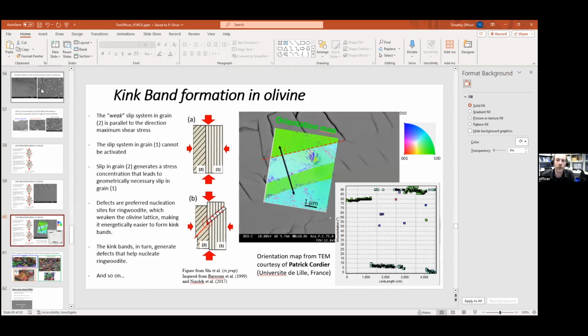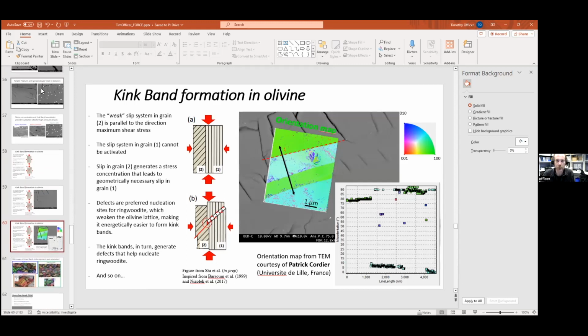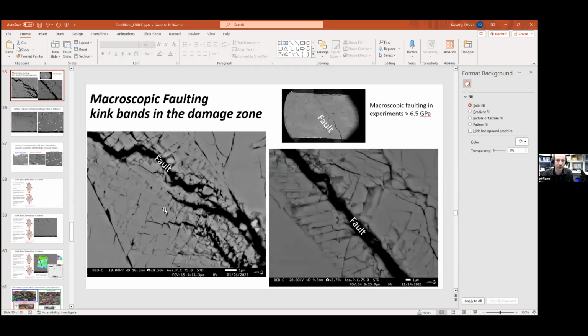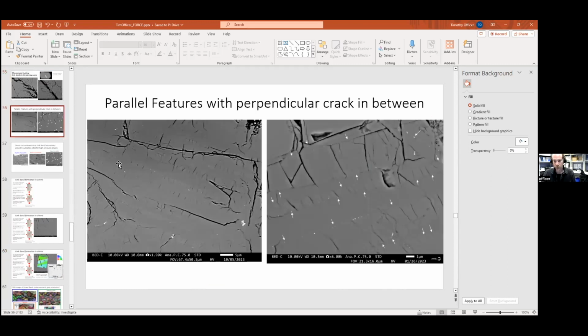If you look at that picture before, you see how there's something geometric about how it fractures. All of these things are at a different orientation. We see these long, thin bands where the high pressure phase forms. There's a band here, and then another band that has a bunch of cracks in it that are all in the same direction. Then there's another band, and another band with cracks. All of these things are at a different orientation.